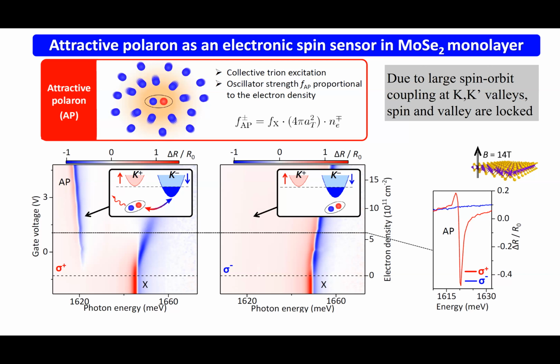At 10 Tesla, I would have a cyclotron energy of maybe 15 milli electron volts and a Coulomb energy of, say, 5 to 10 milli electron volts. Here, Coulomb energy is 230 milli electron volts, cyclotron is 2 milli electron volts. So you cannot describe the physics of excitons or trions or polarons by only considering single Landau levels. In gallium arsenide also, this is not always the case. If you go to holes or to aluminum arsenide, Mansour Shayegan has this experiment with X valley, then you can actually get very large rs parameters. And if you apply a magnetic field, you see Wigner crystal, etc., where many Landau levels function.